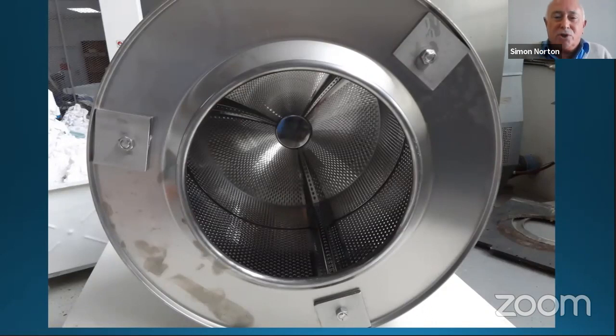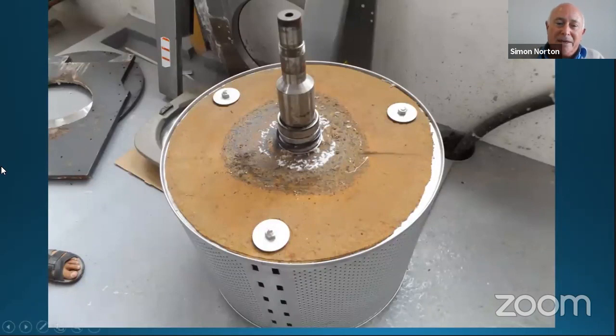The drum, because it's loaded with so much water and washing, has to be very well balanced. And the drum had a balancing disc. Now, this was definitely a design fault. If you look on the back here, this is a carbon steel balancing disc attached to a stainless steel drum. Now, when we first came to look at this problem, we thought that we might have a galvanic corrosion problem. And I think the reason I showed this, although it's not a stainless steel failure, is that I wanted to introduce the concept of galvanic corrosion, because that can occur with stainless steel.